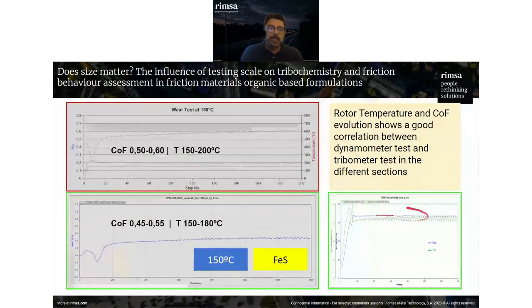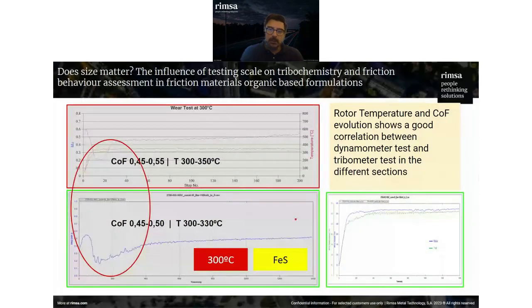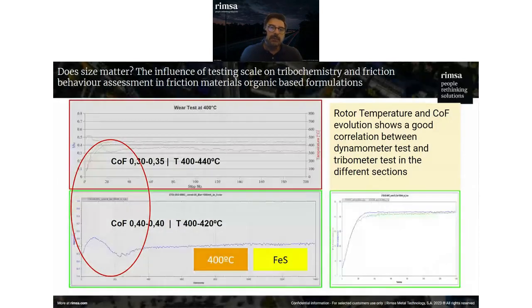Because of representation, we are showing a separate line. Here are the results of this iron sulfide at 300 degrees, and we have also a close coefficient of friction, and also we have this drop. There is some slight variation, but we see this evolution of the coefficient of friction. So there is some tribochemistry going on here. And at 400 degrees, we have a very, very good correlation in the evolution of the coefficient of friction on the full-scale dyno and the tribometer.